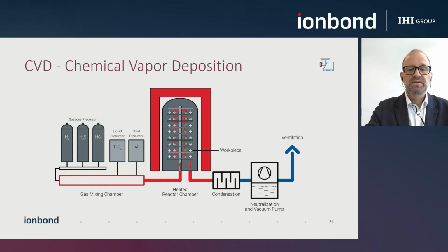It is actually a flow of vapor, a flow of gas in the reactor. We are pulling these precursors by means of the vacuum pump through the reactor and out of the reactor again. And this way we can create mixtures of gases and create multi-layers. However, after having reacted in the dome, these gases are condensed and neutralized, and cleaned gases are then ventilated out of the system. In contrast to PVD, the CVD is not a line of sight process. So with the CVD, we can also coat inner surfaces of goods or drill holes, for example. So CVD is adding complementary coatings and applications to the PVD coating portfolio, so to say.